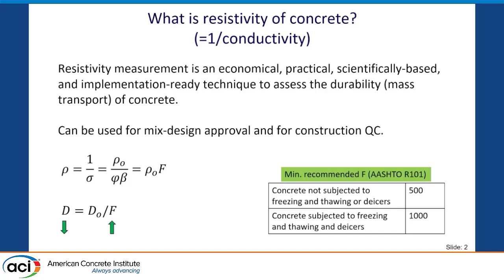I'm going to talk about how this is measured, but very quickly, the resistivity, which is the inverse of conductivity, is a function of the resistivity of pore solution and a combination of porosity of concrete and connectivity of the pores. And this, 1 over phi beta, is also written as the so-called formation factor, F. This formation factor can be directly related to mass transport, to the diffusion coefficient of concrete. For example, your chloride diffusion coefficient is equal to a constant number divided by formation factor. As you can see, a higher formation factor means a lower diffusion coefficient or longer service life.